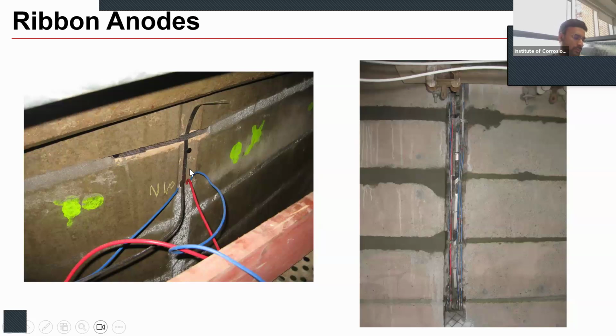Ribbon anodes are typically available in a range of widths, starting from 10 mm, 13 mm, 12.5 mm, up till 20 mm, and pass about 2.8 to 5.5 milliampere per linear meter of mesh width, depending on the mesh.